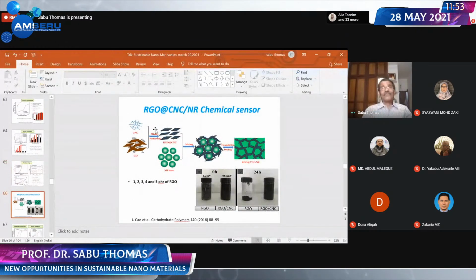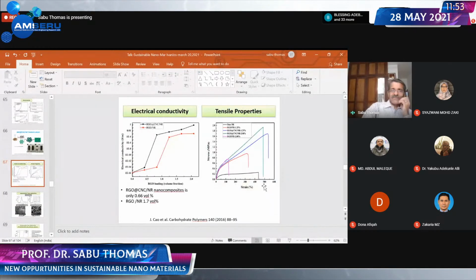I want to show you another example. A combination of graphene oxide and nanocellulose. The same protocol: you take nanocellulose crystal and graphene oxide, mix with the natural rubber latex, and make a composite. And you see, if you use reduced graphene oxide alone in natural rubber, you have a percolation process beyond 1% of RGO loading. But if you combine RGO and nanocellulose, you see the percolation is shifted to a lower concentration of RGO. And mechanics were superior because RGO is dispersed well in rubber.